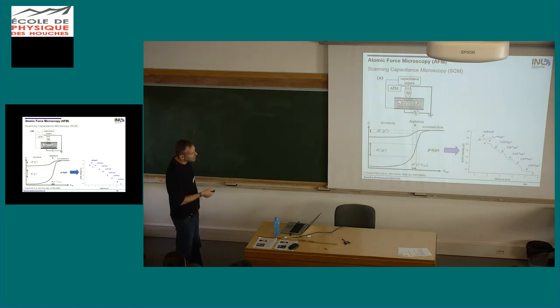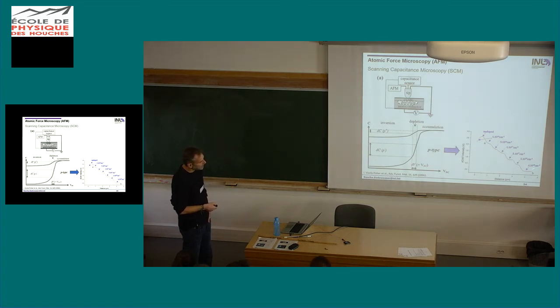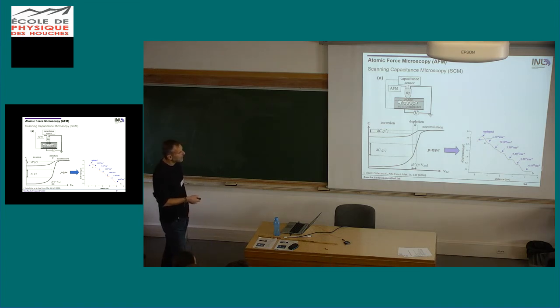So you can do a calibration curve if you have a sample where you know your doping concentration. So this is like a stack of materials with different dopings that you can then scan. And you see here we have a low signal for high doping here, and then as the doping goes lower, so here we have 4 times 10 to the 18, here 10 to the 16, we get more and more and larger dC/dV intensity.